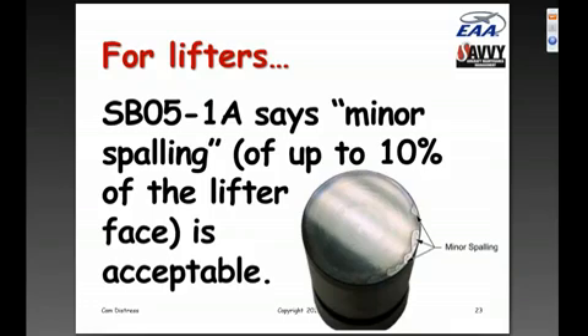I personally don't agree with this guidance. On a Continental engine, it's so easy to change a lifter that if any defects at all are seen in the face of the lifter, I personally would just go ahead and change it. It's not a lot of work. The lifter isn't very expensive, and we want to give the cam the best possible chance of survival. So personally, even if I saw a small amount of spalling on a lifter, like pictured here, I would change it. But Continental's guidance is that spalling of up to 10% of the lifter face is acceptable.